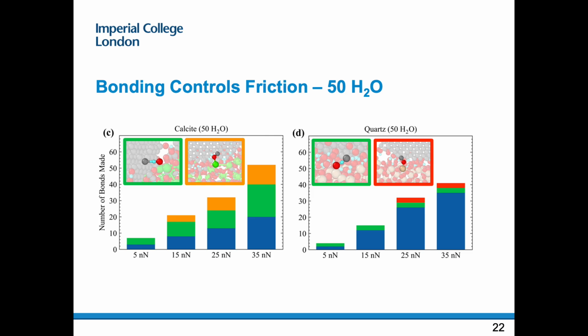We can see that the total number of interfacial bonds increases for calcite and decreases for quartz when water is added to these systems. Mainly, there seems to be a high affinity for bridging bonds to form in the calcite system and a reduced affinity for silicon directly bonding with oxygen in the quartz systems. The insets are color-coordinated snapshots of these bonds in the respective systems.